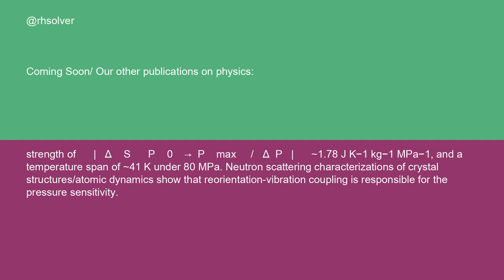Neutron scattering characterizations of crystal structures and atomic dynamics show that reorientation-vibration coupling is responsible for the pressure sensitivity.